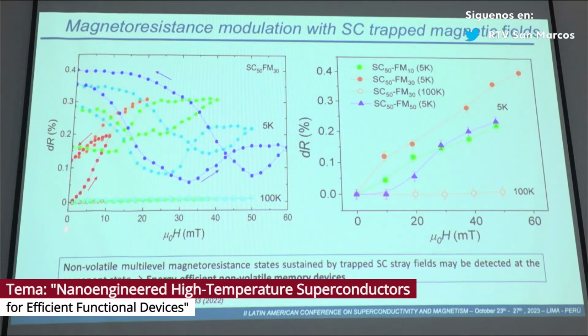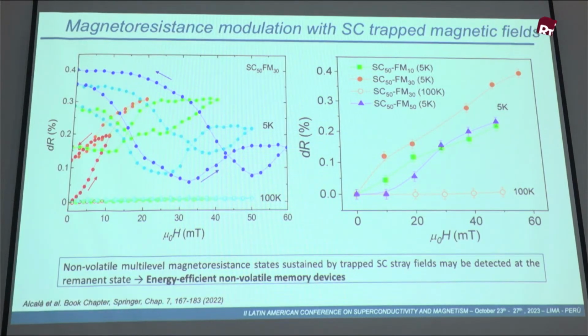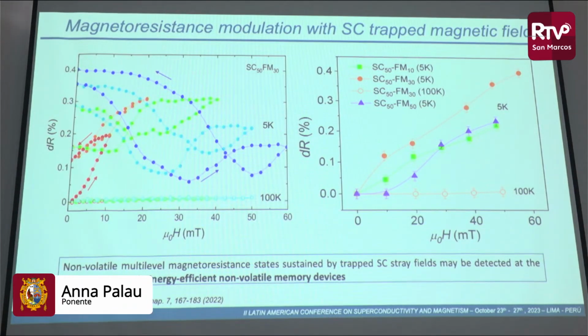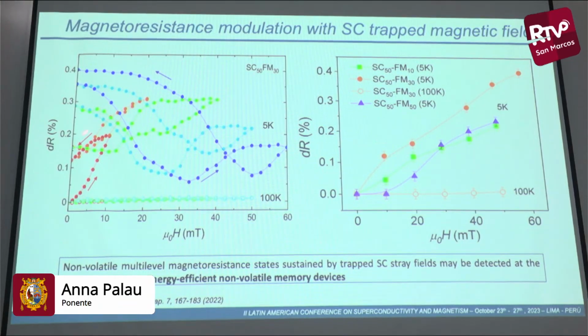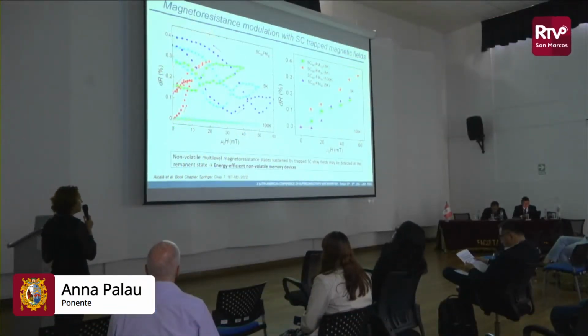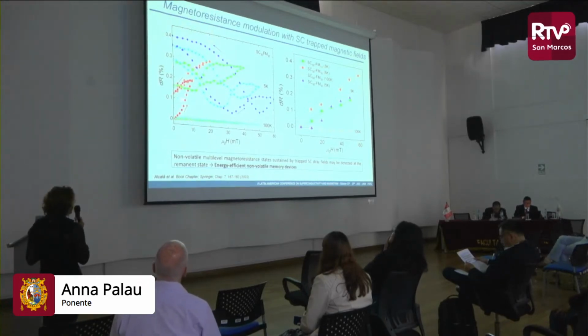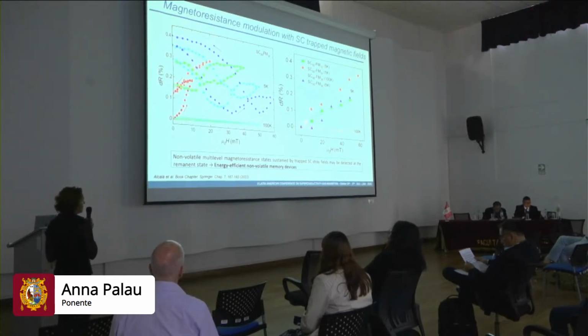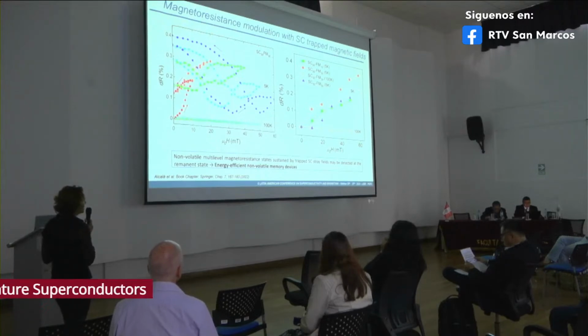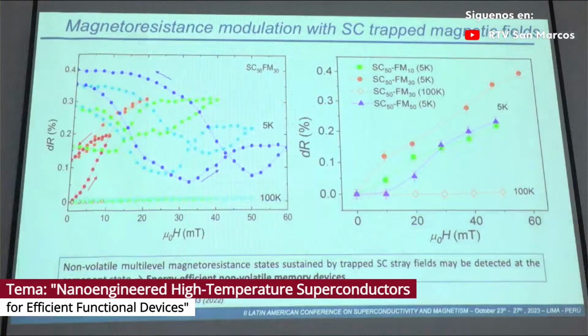And this would be the result, the resistance as a function of the applied magnetic field. If we do all the tests above Tc, we don't see any change in the magnetoresistance because we don't introduce any change in the magnetic structure of the magnetic system. But when we do the experiments below Tc, what we have is penetration of flux inside the superconductor, and we have several minor loops that are totally reflected in the magnetoresistance of the ferromagnet, and so many different ferromagnetic states can be stabilized at zero applied field. This would be at remanence when we perform different loops in the superconducting system.